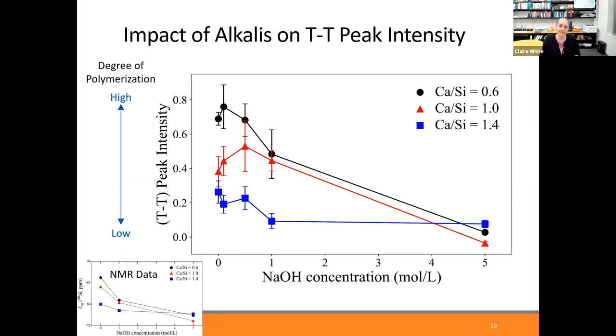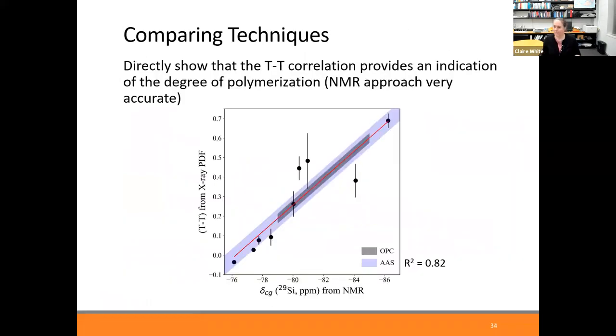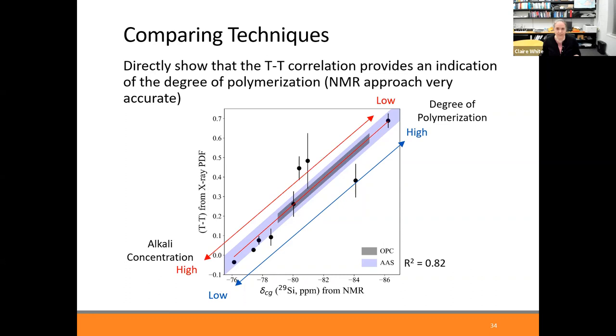We can actually look at local structure in terms of coordination, whether it's more coordinated or less coordinated with other silicate units, using this X-ray technique. When we compared with the NMR results, which is shown on this plot, there's a trend there. PDF analysis, pair distribution function analysis, is not going to be as accurate as NMR. But it was interesting to see that we could get this correlation between the two. And so what we find is when you have a high degree of polymerization, we have low alkali concentration, low amount of sodium, whereas if we've got a high amount of sodium, we have a low degree of polymerization.